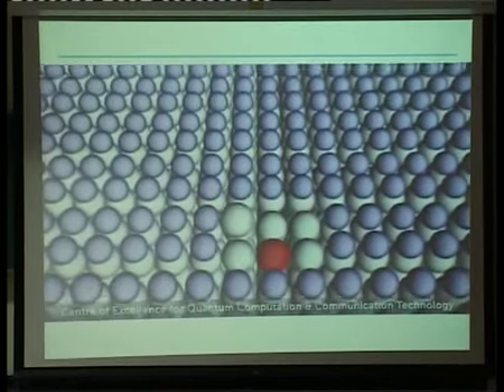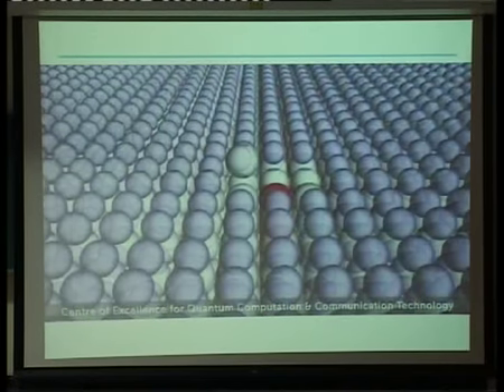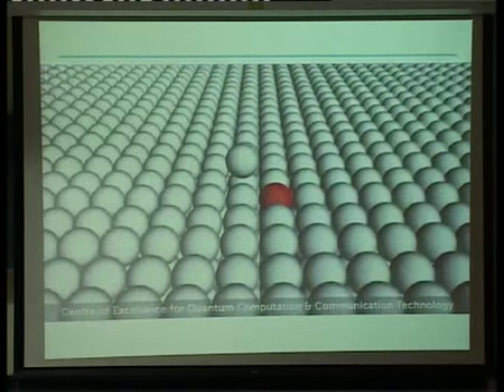So that really shows you in the STM imaging what's happening. We then get rid of the hydrogen resist, and we encapsulate with silicon, and that gives us this nice crystalline environment for the qubit state.